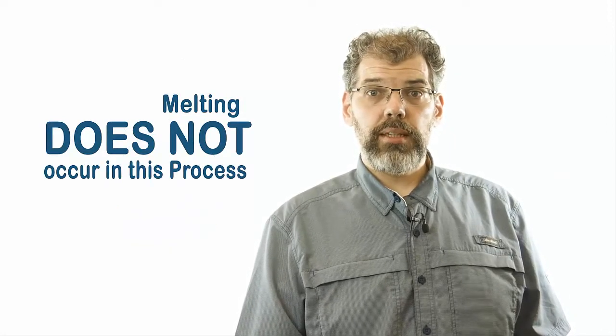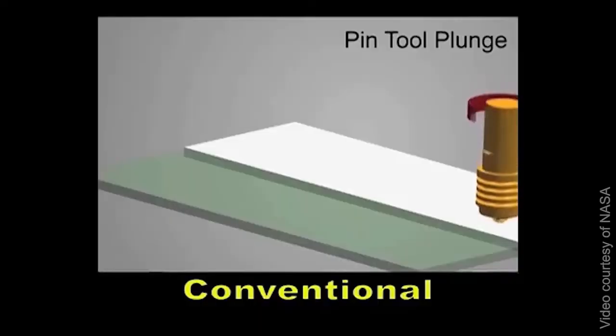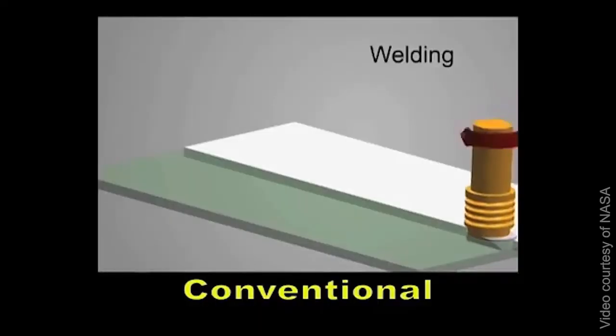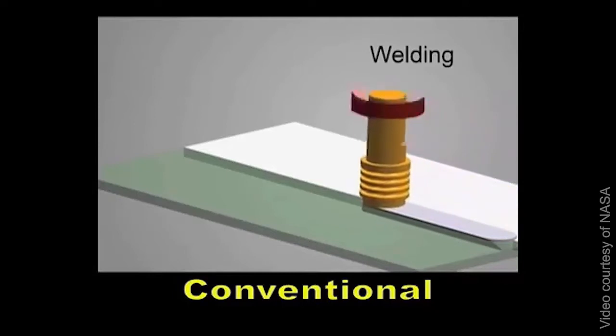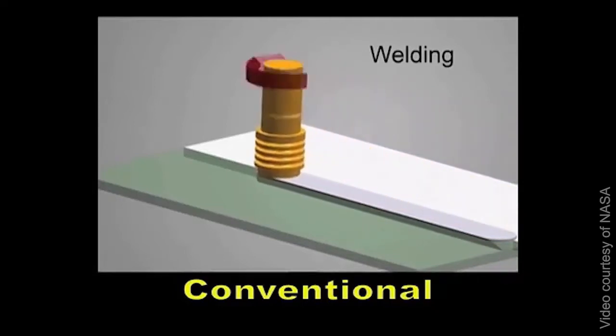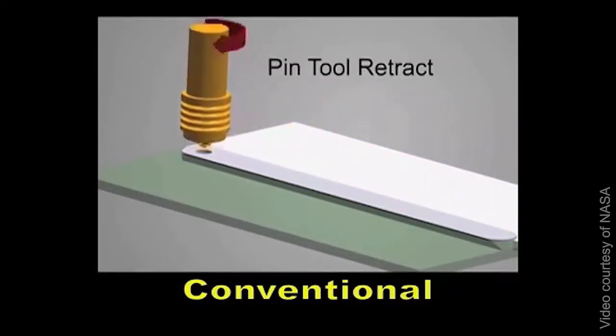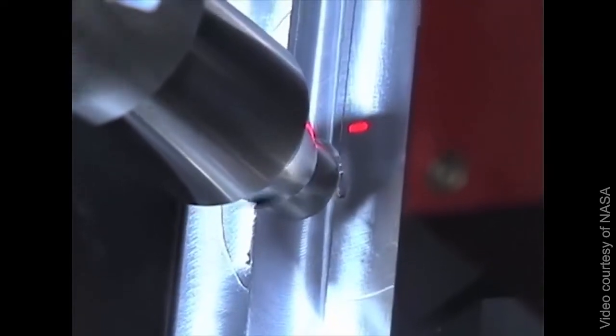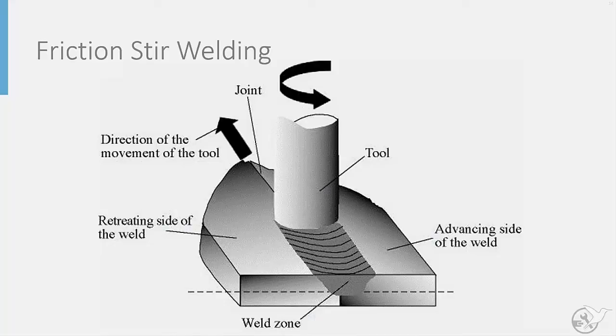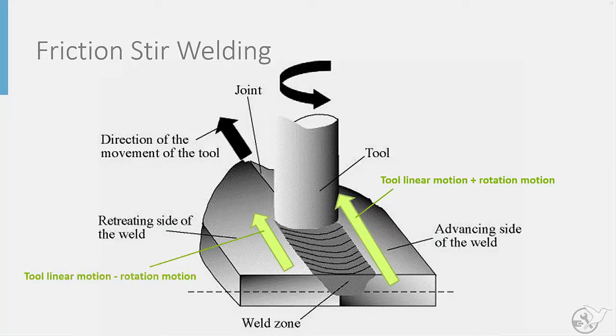As melting does not occur, lower temperatures are needed in the welding process, opening up a wider range of weldable metallic materials. The friction and stirring action is provided by a rotating pin tool that plunges into the material being joined. As the tool both moves linearly along the joint and rotates, the speed of the material is faster on the advancing side of the weld compared to the retreating side of the weld. This difference in speed results in a difference in the mixing and thus overall properties on each side of the weld.